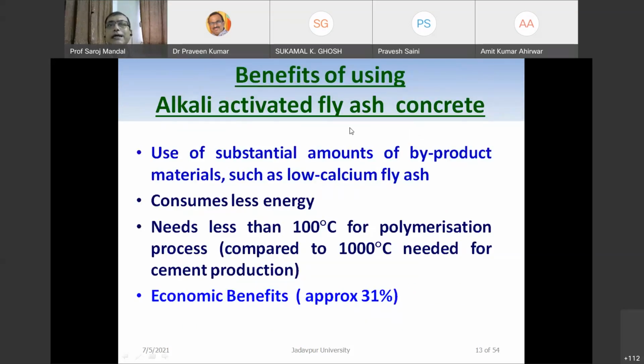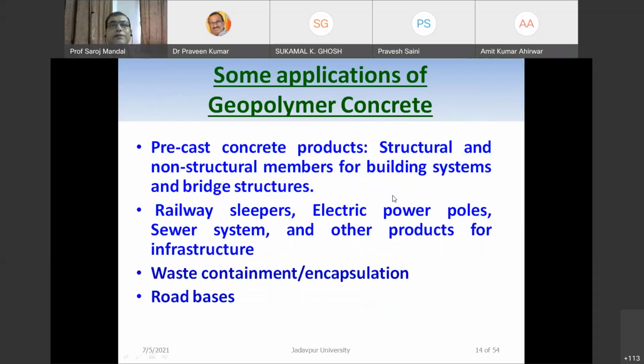Now, what are the benefits of using alkali activated fly ash concrete? I have already discussed the use of a substantial amount of byproduct material such as low calcium fly ash. So I am consuming this waste. I am using less energy and need less than 100 degrees C for the polymerization process, compared to 1000 degrees C needed for cement production. Although heat is required in these cases, it is not more than 100 degrees C, right? But in cement production, about 1000-degree temperature is needed. So naturally, you can see what benefit you are getting here. And I will show you later that the economic benefit is approximately 31%, and further benefits can be added. I will discuss this later on.